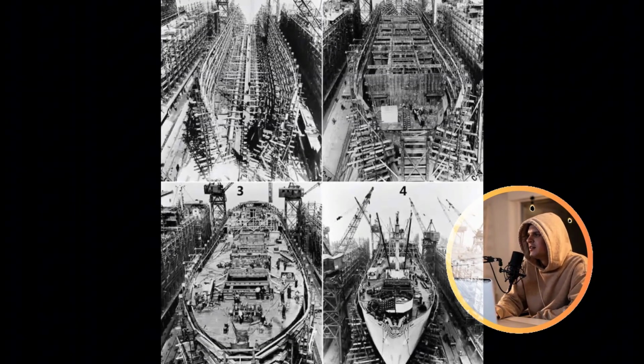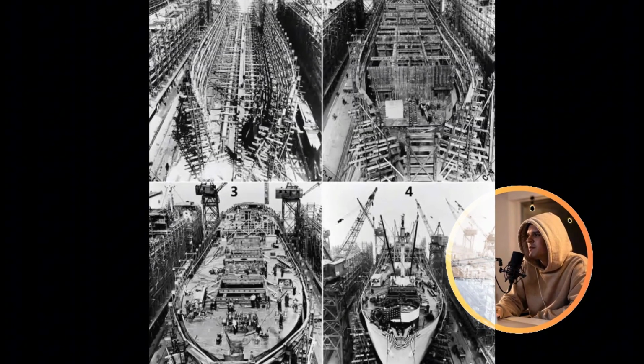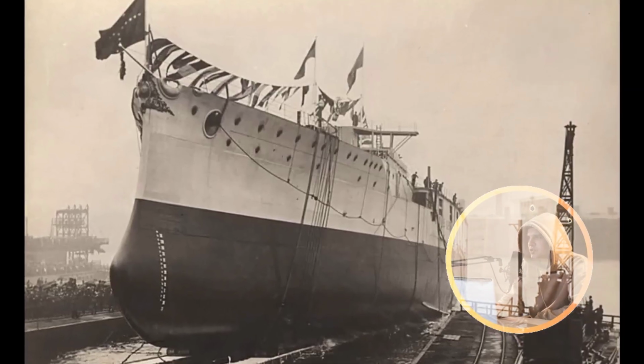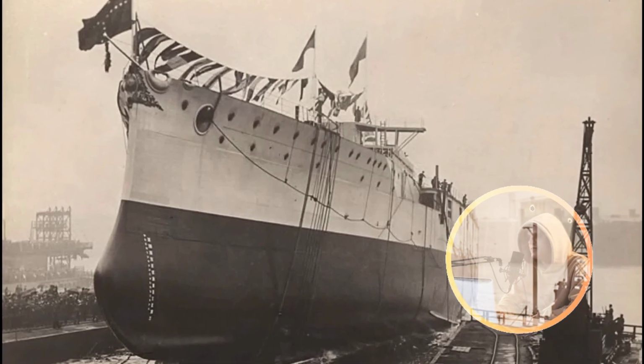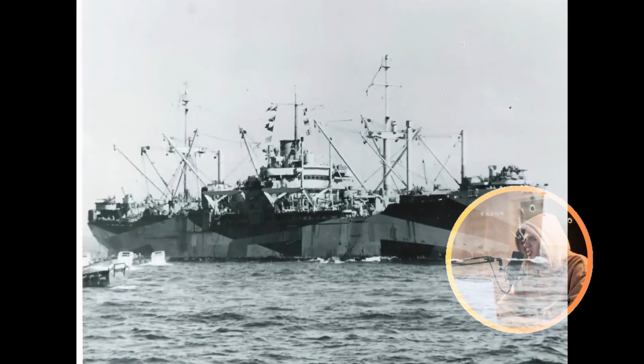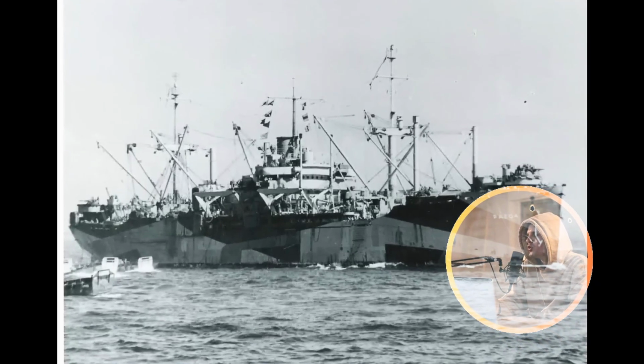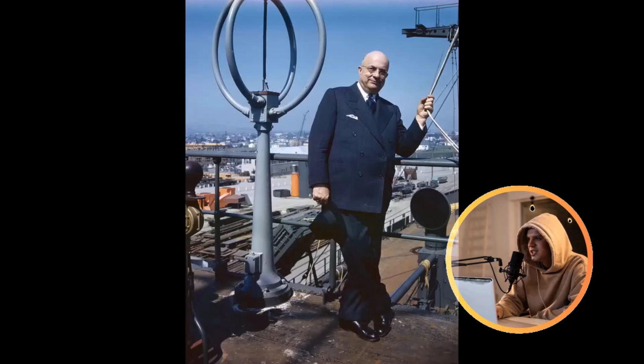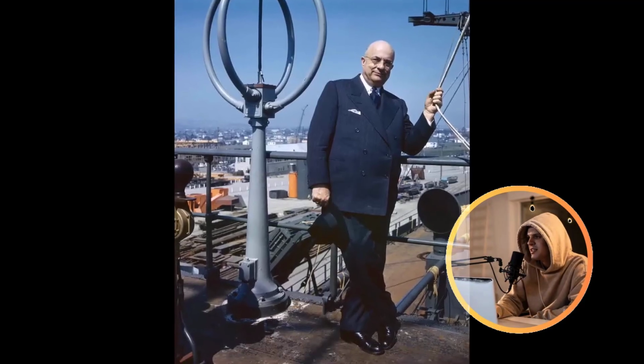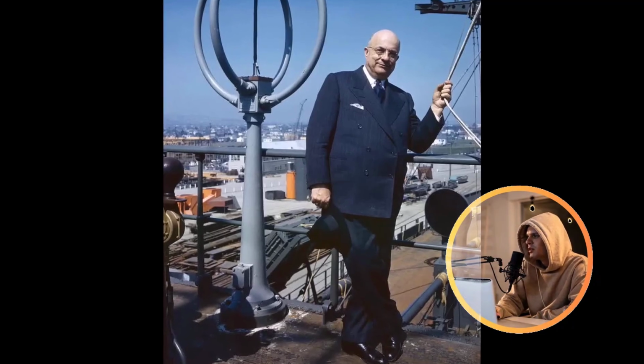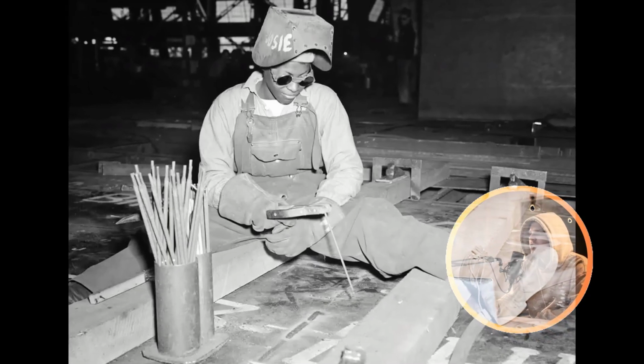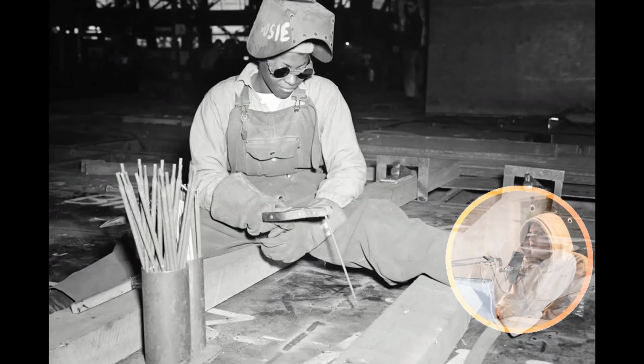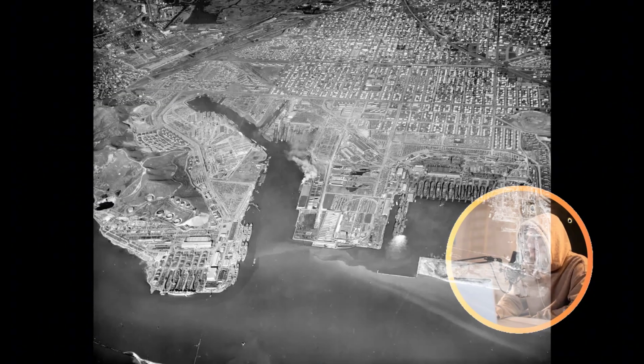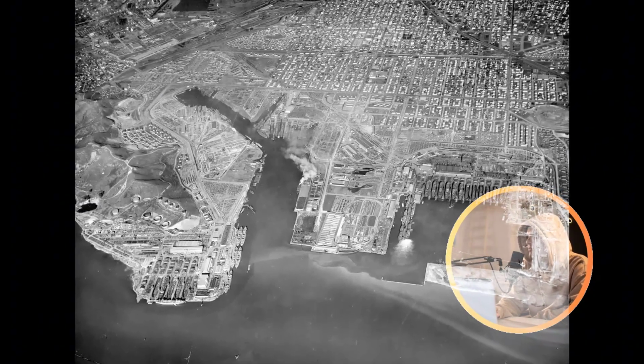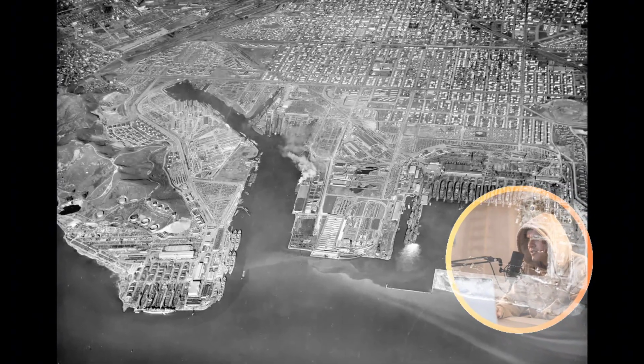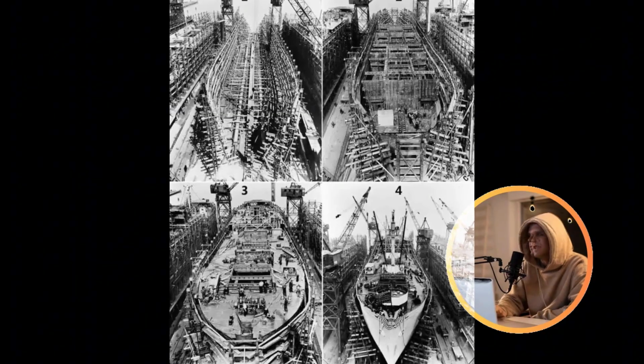The existing prefabrication system was dramatically expanded and refined. Instead of the previous method of welding large sections directly on the ways, where controlling sequencing was inherently challenging, Kaiser's meticulous planners ingeniously broke down Victory ships into much smaller, more manageable modules. These modules were then constructed in specialized, dedicated workshops. For instance, a single bow section might comprise as many as 50 separate prefabricated assemblies, each meticulously welded under strictly controlled conditions using optimal sequences. Crucially, these assemblies were then stress-relieved in heating ovens before their final integration.